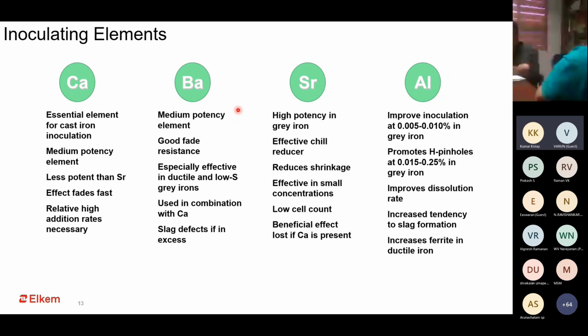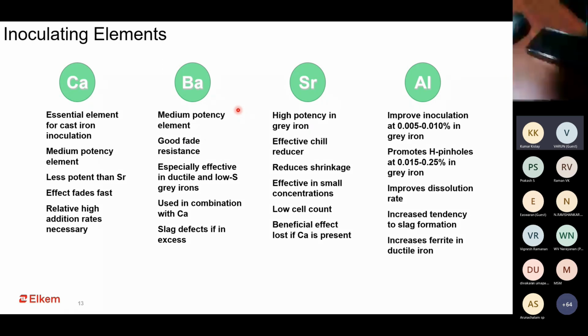And this is one of the main reasons why strontium inoculants are not used in ductile irons, because ductile iron treated with ferrosilicon magnesium would have some calcium inherent in it. That is the reason why strontium does not behave in the manner it should in the case of SG iron. So a strontium inoculant is more commonly used in the case of grey cast iron.